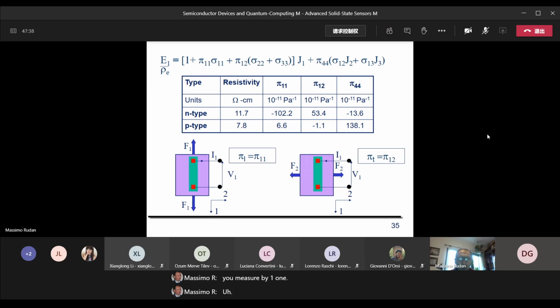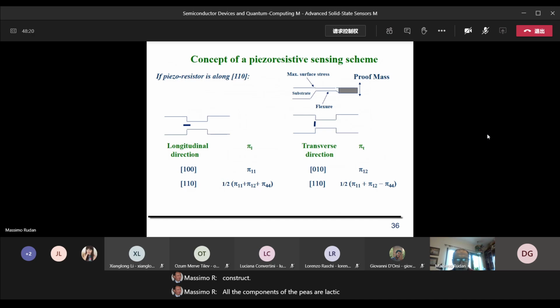If you instead want to measure pi 1,2, what you do is simply that you apply a stress over face number 2. So you have sigma 2,2 is different from 0, okay? Whereas sigma 1,1, sigma 3,3, and the mixed components are zero because you do not have shear forces. So in this case, you measure pi 1,2, and so on and so on. So by this, you reconstruct all the components of the piezoresistive tensor, okay?